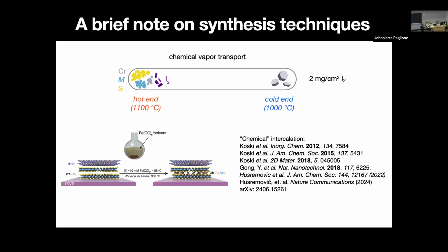Where you use some soft chemistry, which is some of the stuff that we've looked at a little bit, to intercalate, versus growing at 1,000 degrees or 900 degrees. So as an example of that, I mentioned that predominantly the intercalation compounds are all the 2H structure. And so if you try to grow, let's say, iron intercalated or chromium intercalated tantalum sulfide under conditions where, if there was no intercalant, you would end up with a 1T phase, which has the CDW, if you try to do the CVT, at least for us and others, you always end up with a 2H phase. It just goes to that. But we're writing this up, but you can do the soft chemistry with a 1T, and you end up with the magnetic material that also has the CDW. Structurally it's a bit of a mess, but it's there, right?